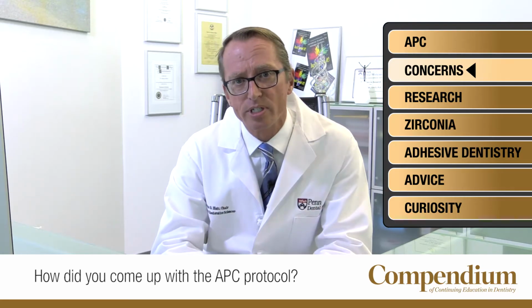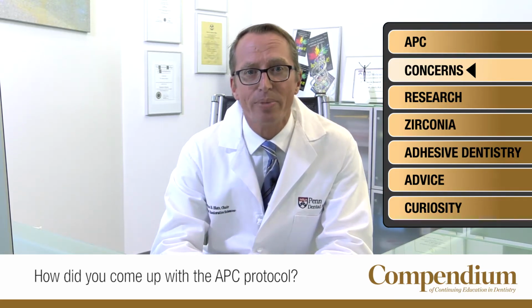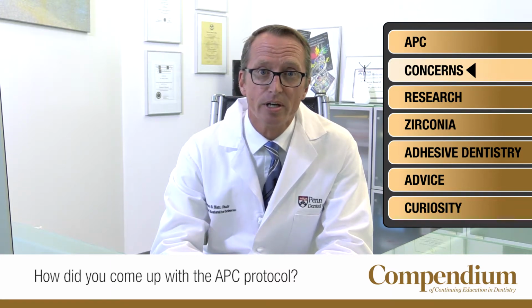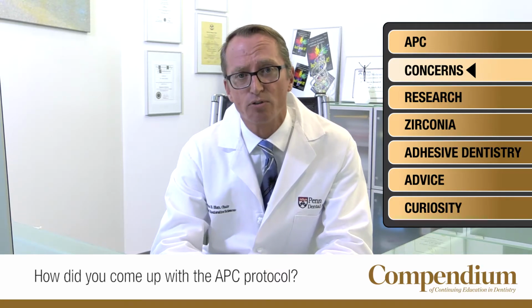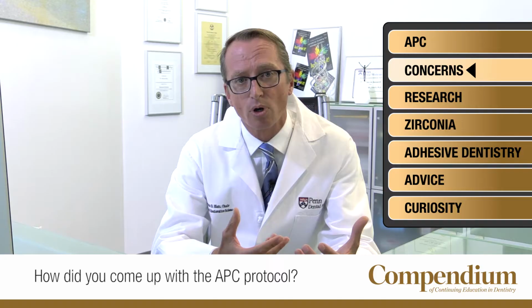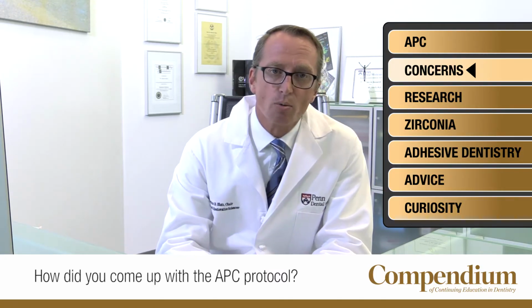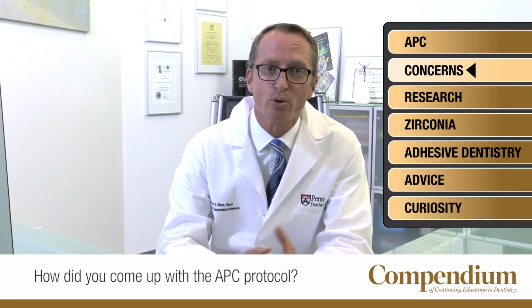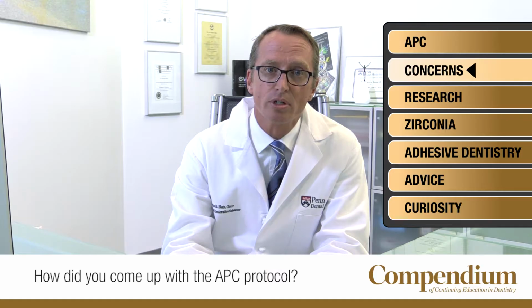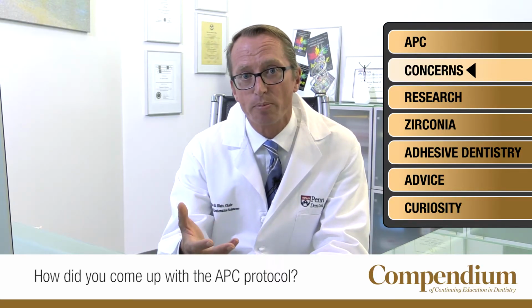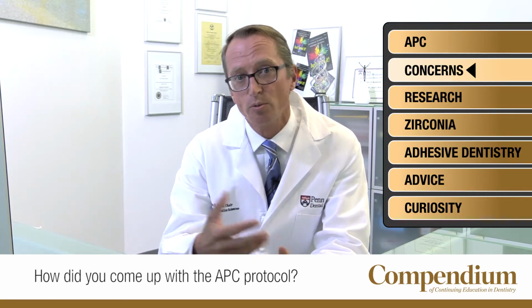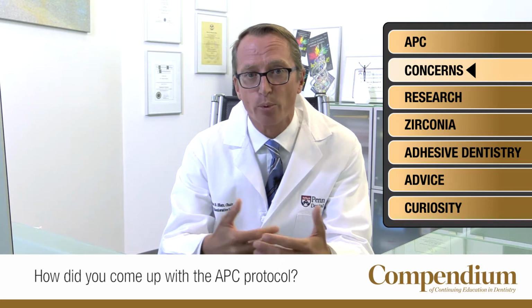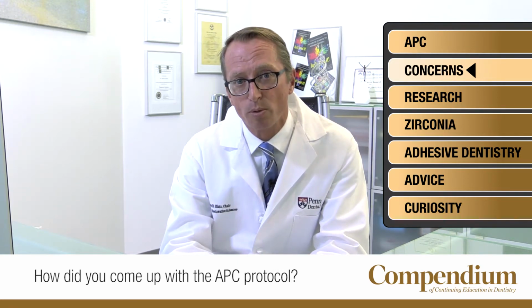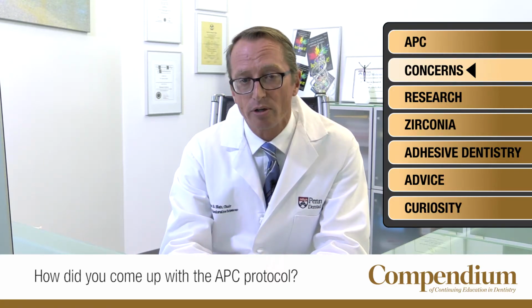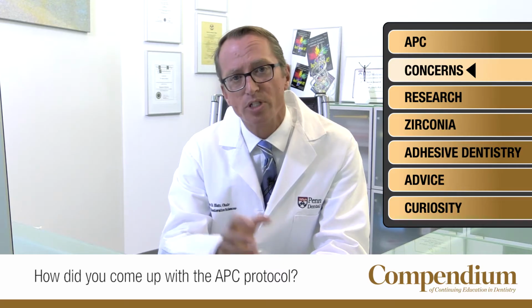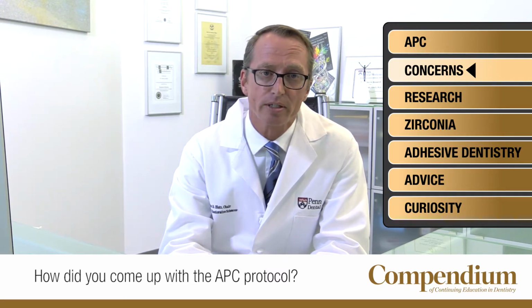So the APC protocol is not something entirely new or revolutionary. It is actually based on all the research we have done over 15 years. And we're talking about tens of thousands of specimens that we have looked at to find out which is the best protocol to bond to zirconia. And interestingly, we almost always come up with the exact same protocol, and that is you need to pre-treat the surface, and typically that's the air abrasion step or air particle abrasion step. Some people say sandblasting. We usually use aluminum oxide for that. Then applying a primer, a priming agent on top of that, followed by a composite resin luting agent, typically dual cure or self-cure. So with all the cements we have tested and all the pre-treatments we have tested, this always has been the quintessential protocol that came out of these studies.